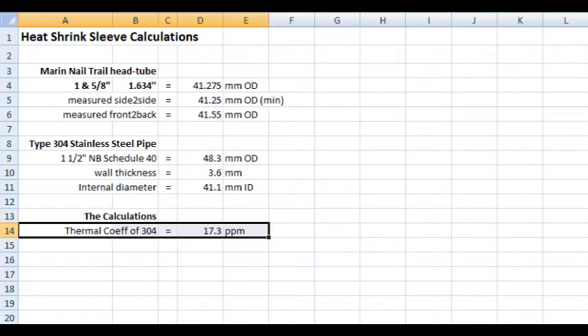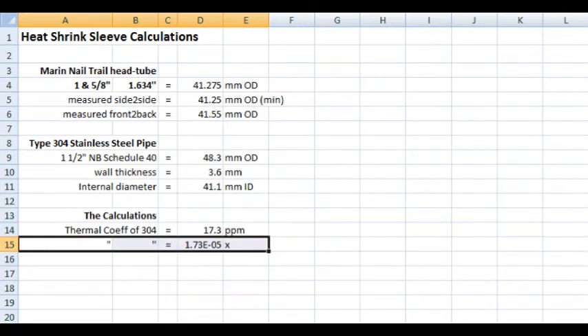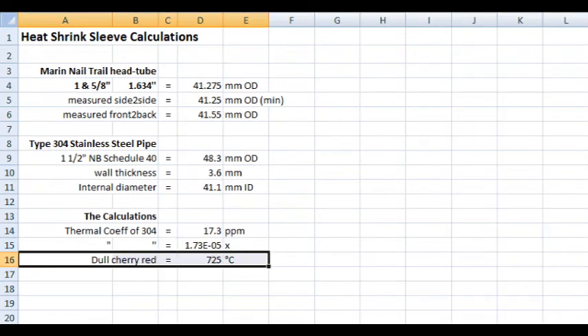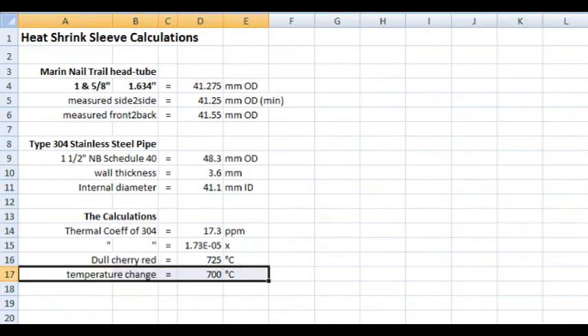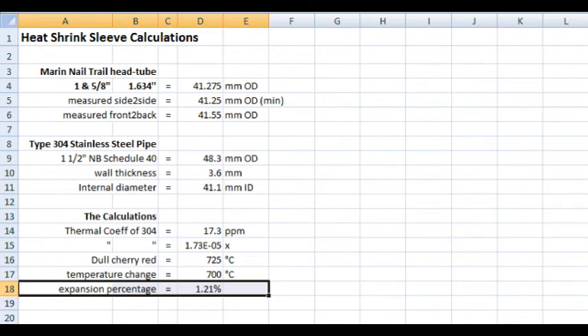The thermal coefficient of type 304 is 17.3 parts per million, so I need to multiply that by 1 times 10 to the minus 6 to get the factor, which in my case here is 1.73 times 10 to the minus 5. Dull cherry red is about 725 degrees C, and we're going to drop it from that temperature down to room temperature. That's a 700 degree temperature change. So you multiply that 700 degree temperature change by the factor 1.73 times 10 to the minus 5, and you get 1.21%. That's how much it's going to shrink.